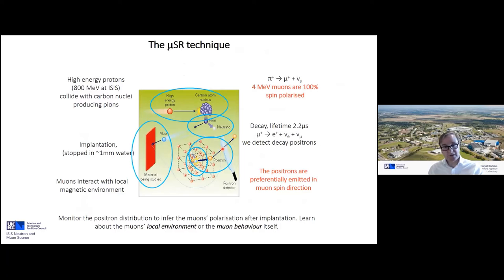They emit some neutrinos and a positron. We detect the positron. And the interesting point is the positron is preferentially emitted in the direction that the muon is pointing at the time it decayed. So you can see if you measure up enough statistics, you're able to back calculate the local environment that the muon must have been sitting in to give you that profile in time.